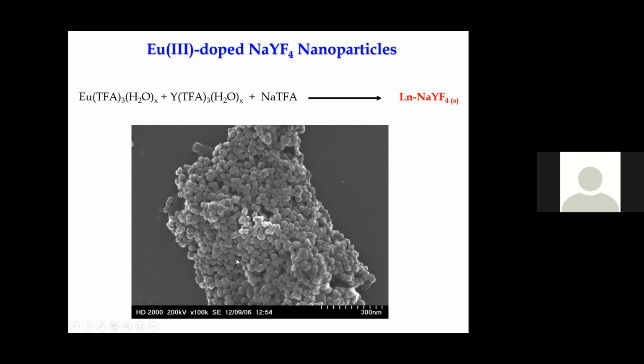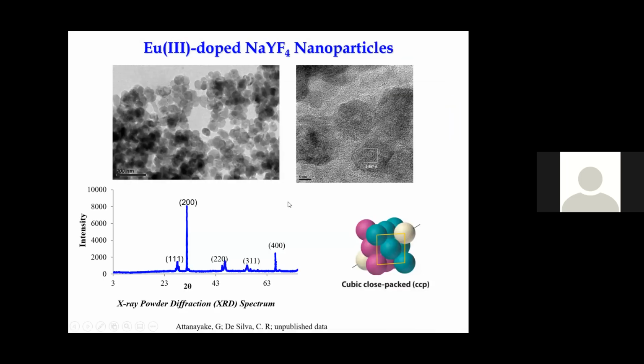This is called scanning electron microscopy. You see these individual balls are nanoparticles. So what we do is we characterize these nanoparticles using these electron microscopy techniques. You can see when you zoom in, you can get one individual nanoparticle on the screen. And we use another technique called X-ray powder diffraction. What we do is we shine an X-ray beam at the material and it gets diffracted because the X-ray wavelength is comparable to the atom size. And you get a certain pattern, we call it a diffraction pattern. You see your y-axis is the intensity, your x-axis is the 2 theta. Theta is the diffraction angle.